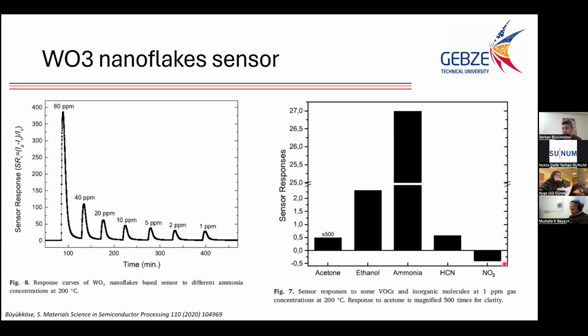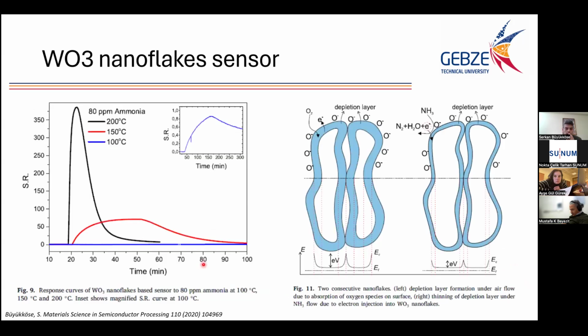Here it seems interesting for NO2. Here NO2 is giving a response in the reverse direction because it's an oxidizing gas. All the others are reducing gases. So an oxidizing gas decreases the conductivity, increases the resistivity further. Actually, you see some other results here. Some temperature dependent measurements here.